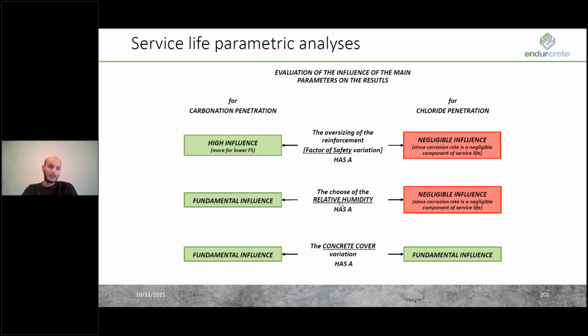parameters. This is simply related to the fact that the 2 different mechanisms that play the fundamental role in carbonation are the rate of corrosion and the penetration of carbonation, that in terms of time are basically the same. While for chloride penetration, we can see that only the concrete cover shows a fundamental influence on the evaluation of the service life. This is related to the fact that the corrosion related to chloride penetration is very high, so the time needed for the corrosion can be seen as negligible with respect to the time of penetration of chlorides.